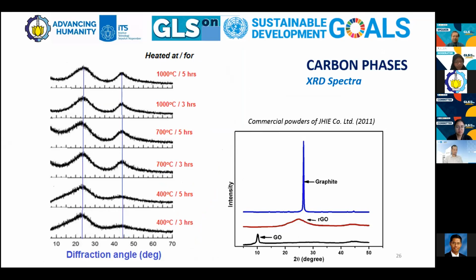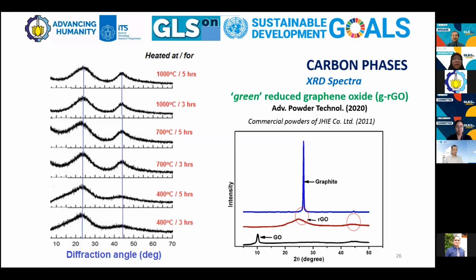Next, the phase analysis of the carbon compound of biochar with heat treatment, varying temperature and holding time, produces a single phase with two diffraction peaks in the XRD spectra at angles of 24 and 43 degrees, which indicate a compound similar to reduced graphene oxide, like this. These two peaks are at 20-something and almost 44, 45 degrees. To differ from RGO made of graphite from mining, we would like to call it green RGO-like carbon. So this is the green reduced graphene oxide.